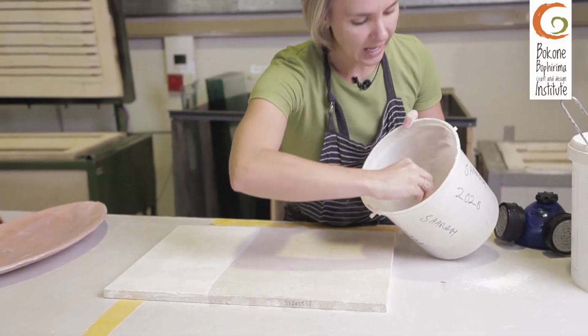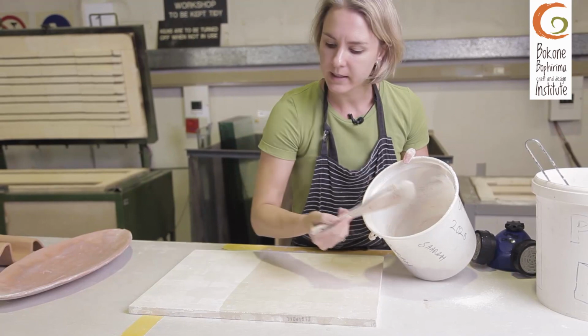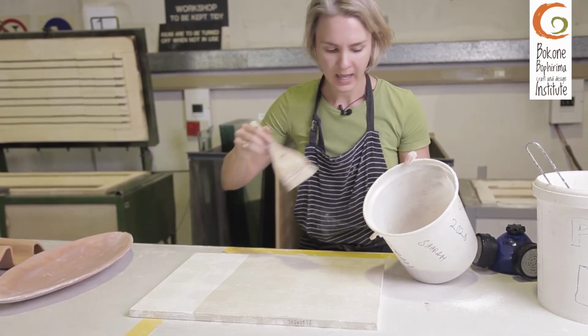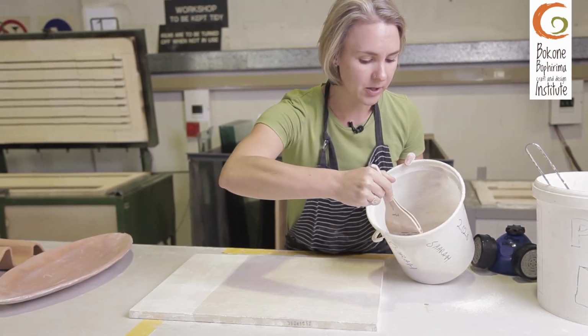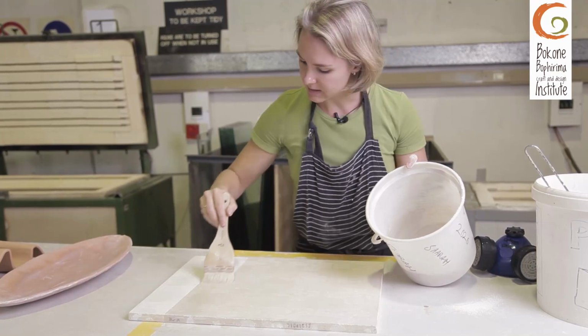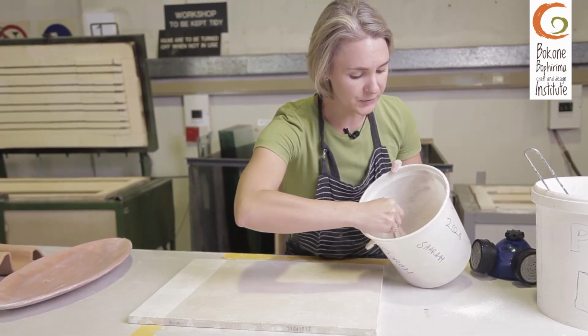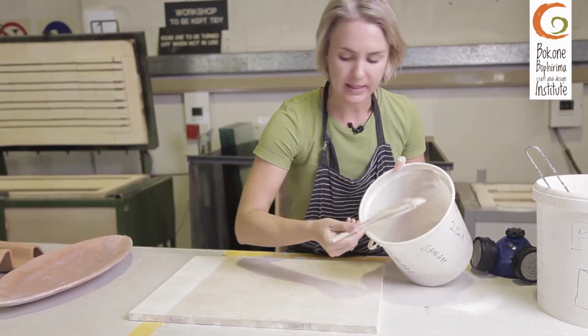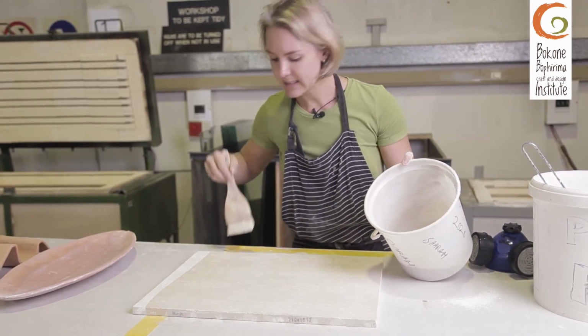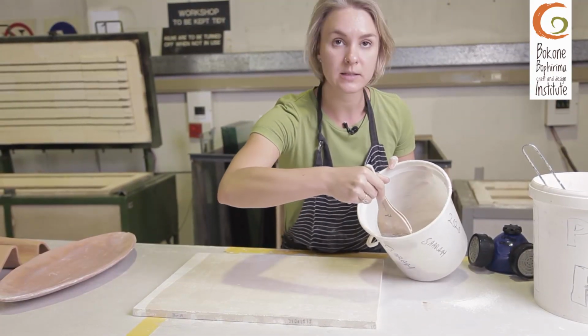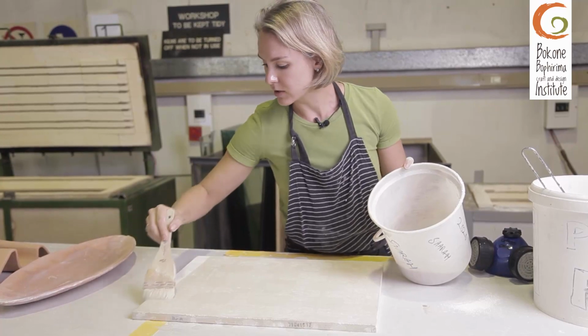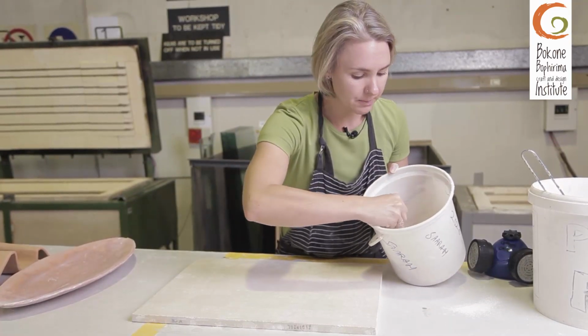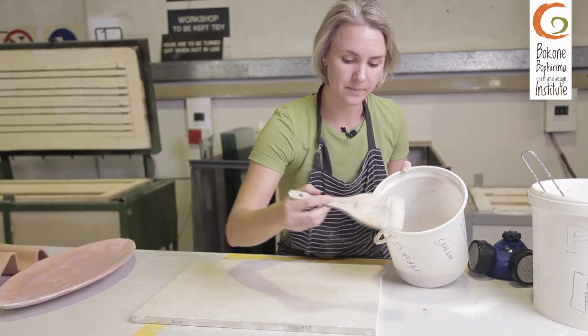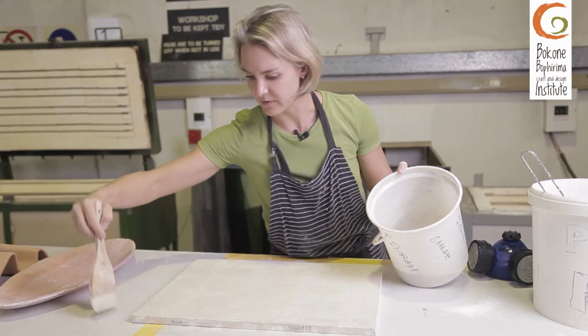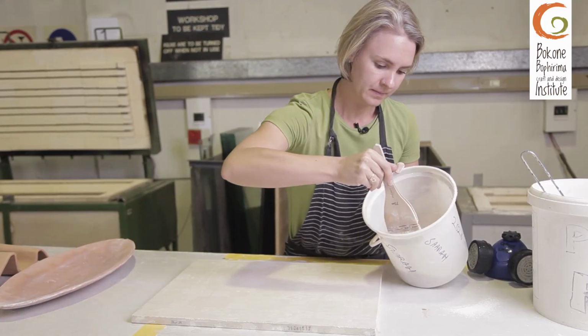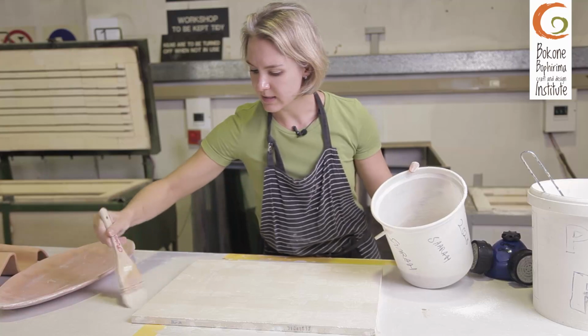So you can see I'm applying one direction first, and I'm going to apply in the opposite direction afterwards, and the reason for doing this is to create fewer brush marks on the surface, because glaze is able to pick up the texture that one puts on the surface. I normally do this 3 times.